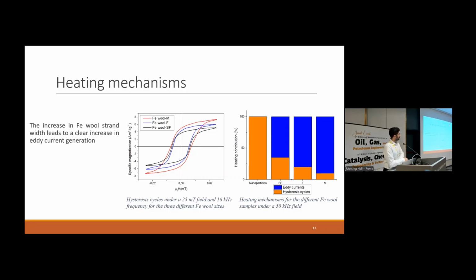After that, for the iron wool, what we observed is that, for example, for the biggest strands, we have around 90% of the heating coming from eddy currents and 10% coming from hysteresis cycles. And for the super thin one, we have around 60% eddy currents and 40% hysteresis cycles.